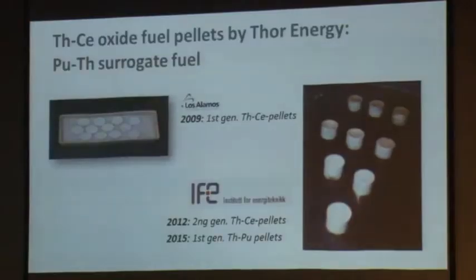We began with surrogate fuel testing, and in 2009 we had a cooperation with Los Alamos National Laboratory where we created thorium cerium pellets. Cerium is a surrogate for plutonium. As you can see up there in the left picture, we were able to create pretty good pellets, but we knew we needed to take another step, so we have another phase where we've begun fuel manufacture testing with the Institute for Energy Technology in Norway. And we concluded that about a year ago. We'll show you a little bit about those. And we're also currently now manufacturing thorium plutonium pellets.